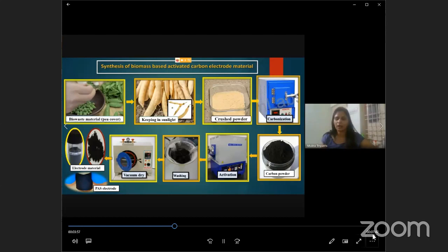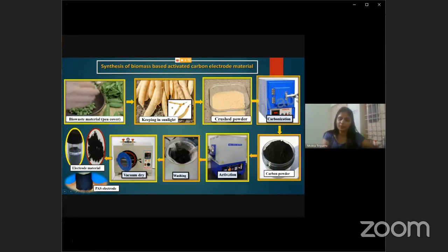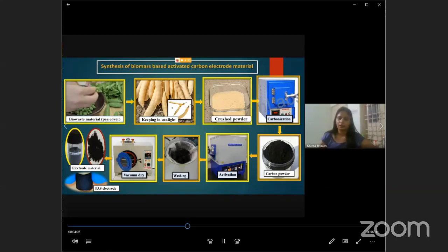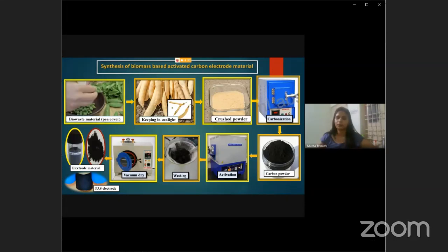So this is the carbon powder, not an activated form. That carbon powder has been activated again by using the tubular furnace. In the tubular furnace we have maintained 800 degrees Celsius temperature for 2 hours. We have set up the program, using nitrogen flow at 150 ml per minute. After 2 hours it is cooled using nitrogen flow for still 12 hours.